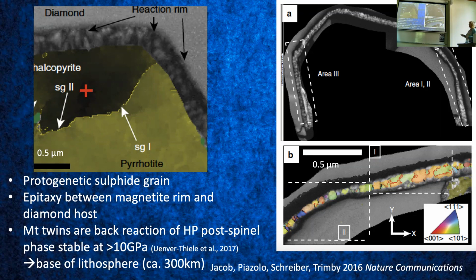So the story is that we had the sulfide, and a fluid came along reacting with the sulfide. This is a redox reaction: it reduced the fluid to diamond and oxidized the sulfide to magnetite. Those formed a reaction pair growing on top of each other. What we learned from these twinning borders here, luckily, is that there is a high pressure phase that forms from magnetite above a certain pressure.